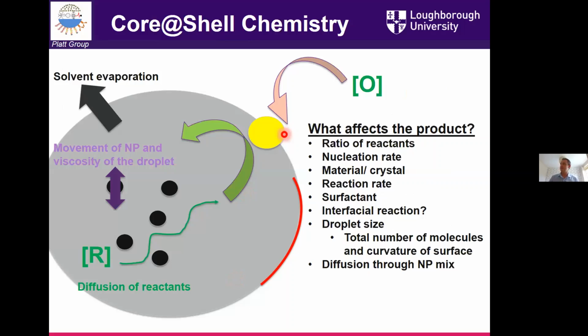You know, the concept that we have these droplets, that we have some metal in the outside continuous phase, the water, that is allowed to go on and react at the interface, if it is truly an interfacial reaction. In theory, this concentration is the easiest thing to control because it's in excess on the outside. And as I change the droplet size here, I change the concentration or the number of electrons potentially possible for the reaction to take place. But I change so many more things in a droplet. I've got the size of the droplet, so I've got the curvature of the interface, and then I've got diffusion to a concave or convex surface of different curvatures.